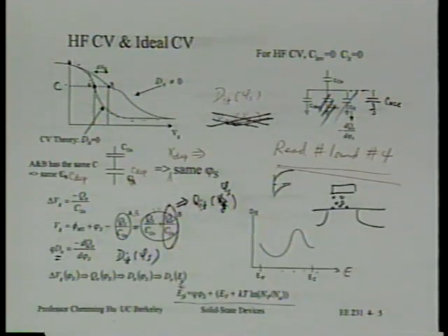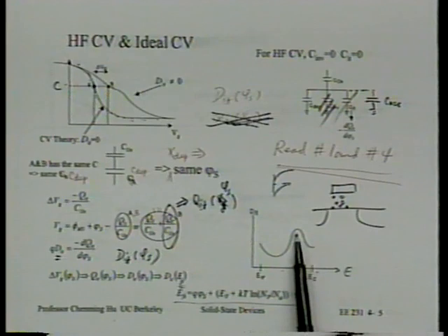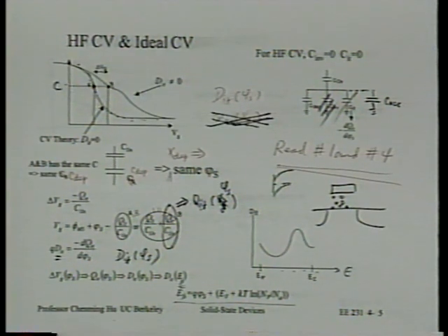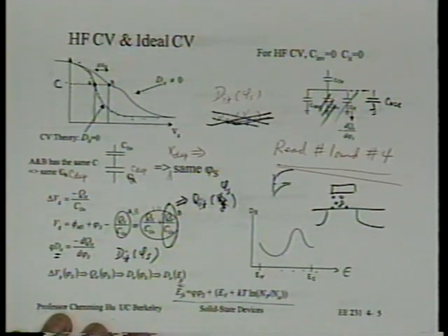It's hard to say what it is. But anyway, we usually do see a continuous curve. This may be due to a particular discrete energy level that is still broadened by its environment. In other words, there's not one very clear bond that duplicates itself exactly from one trap site to another, although they're pretty similar. As a result, they give us one peak.